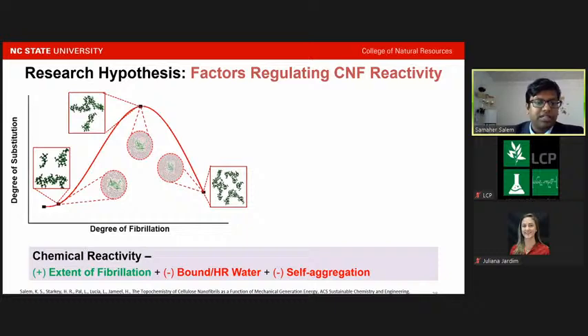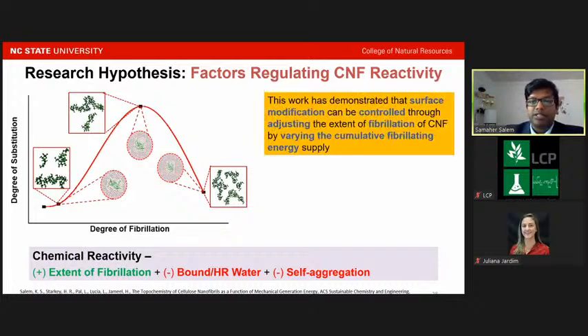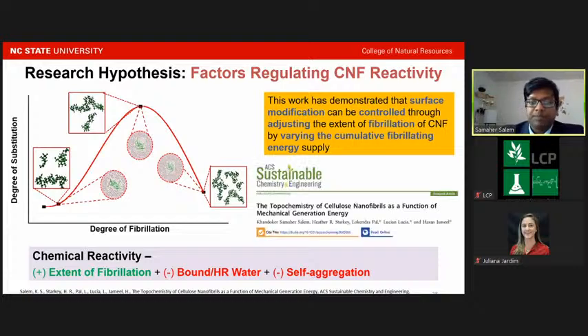And we could say that the chemical reactivity is the combined effect of the extent of fibrillation, the bound water, and the self-aggregation. And this work has demonstrated that the surface modification can be controlled through adjusting the extent of fibrillation of nanofibrils by varying the cumulative fibrillating energy supply. And we have published one journal article based on this work.